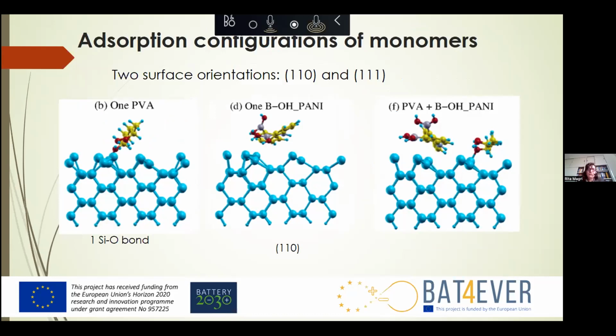So we have considered two surface orientations, and we can see here that the two monomers behave quite differently in proximity of a silicon surface. Most of all, very surprisingly, just the presence of the molecules distorts all the external layers of the silicon surface. The PVA tends to form chemical bonds with the silicon atoms, while the boronic acid doped polyaniline tends instead to rotate only, but the interaction is mainly electrostatic.